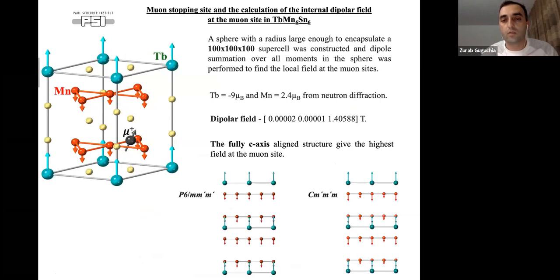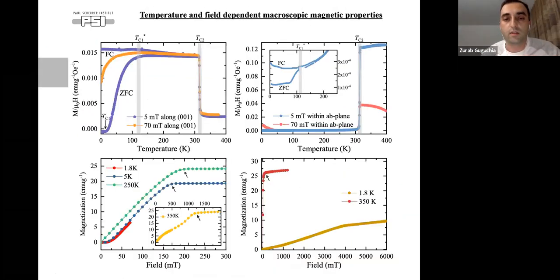And as soon as we get the static patches, even at the base temperature, we don't have 100% C-axis structure. So it's still a grown patch, but not a fully 100% static state. So if you do simple magnetization measurements at low fields, if you apply field along the C direction, you see that there is a hysteresis below 120 Kelvin, below which we see the slowing down process. And these magnetic fluctuations can also explain this, because in this region, when we have static domains in a zero field cooling, the system minimizes the macroscopic magnetization.